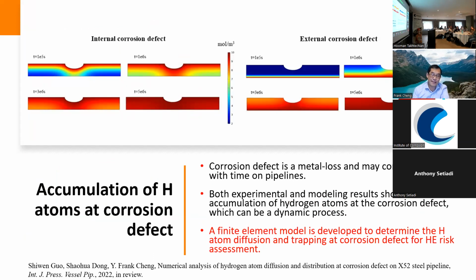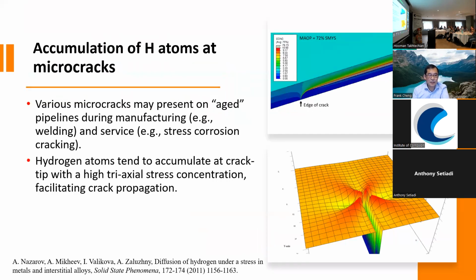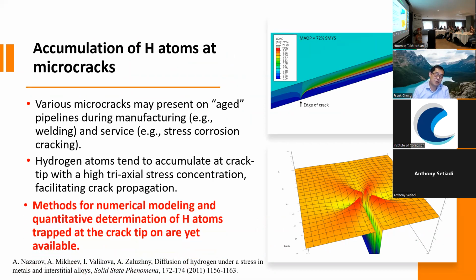You can also see from these simulation results that no matter whether the corrosion is an internal or external defect, hydrogen atoms also tend to accumulate at the corrosion area. That makes the local hydrogen reach a certain concentration value, and consequently hydrogen-induced cracking tends to happen at corrosion defects. So, I will speed up and quickly wrap up. If the aged pipeline contains microcracks, the simulation results also show that the microcracks, because of local stress concentration, can trap hydrogen and make the local concentration reach a certain value.